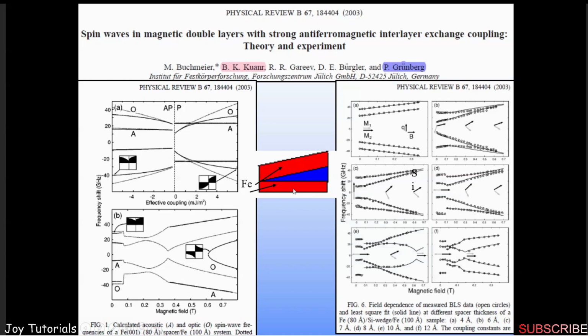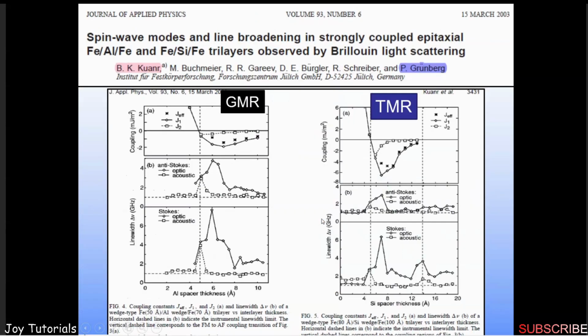This is just one structure, but you have a different variety of spacer layers, starting from 0 chromium layer to about 20 angstrom of chromium layer or silicon layer. So this is the theory for this, the anti-phase or the phase. Through the fitting of this, one can find out what kind of coupling it exhibits through this structure. This is the left-hand side, the GMR structure for the iron aluminum, and the right-hand side, the TMR structure through the iron silicon. Through the fitting, one can understand what is the GMR value or the TMR value or the exchange.